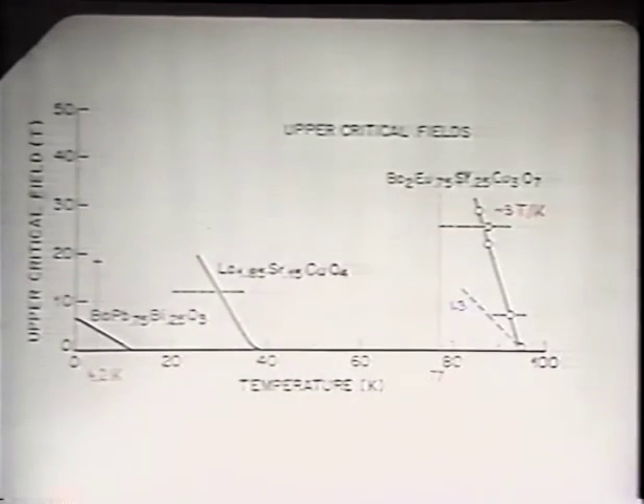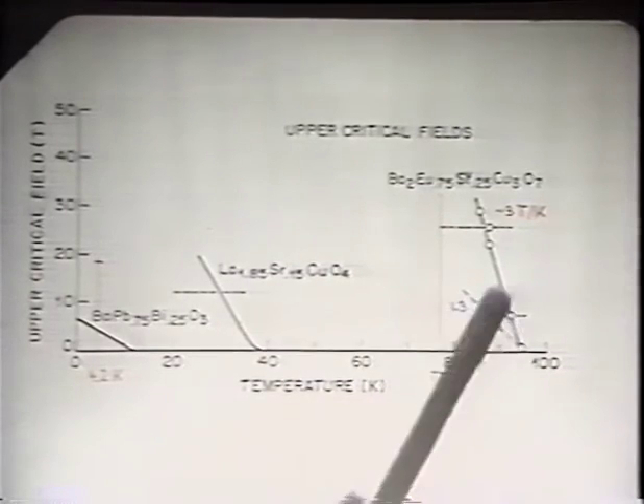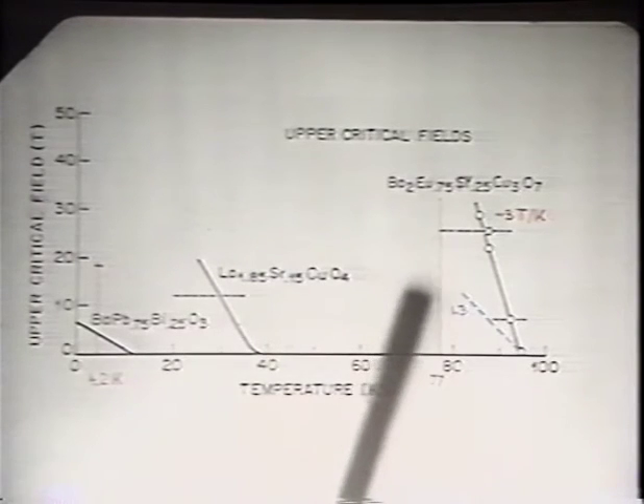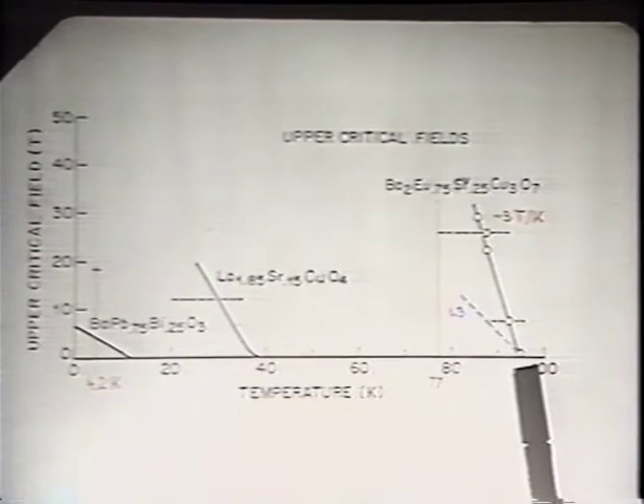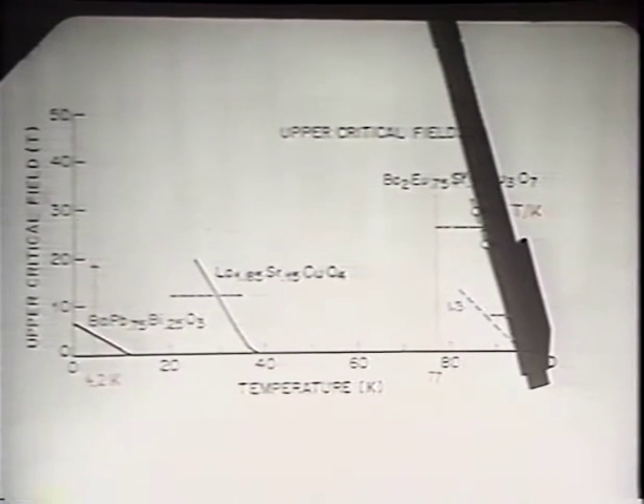And if we want to do that, one aspect is looking at the upper critical field. That's a collection of the upper critical fields, again, for the three favorite oxide superconductors. Just concentrate on the higher one, the highest TC material here. That's the blue line, just for the barium yttrium copper oxide. We substituted part of the yttrium by europium and found an upper critical field slope which is roughly 3 times higher, taken at the midpoint. You can imagine where it extrapolates to. It goes to something like 2 megagauss or so, if you extrapolate it down to T equals 0.